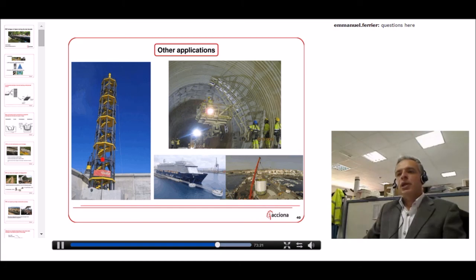The columns are made of carbon fiber pipe produced by pultrusion. The floors here are glass fiber sandwiches manufactured by Resin Infusion. Here you have these stiffening rings made by glass fiber pultruded pipes, and these slabs made by carbon fiber laminates produced by Resin Infusion. And this spiral staircase here, the steps are made by a sandwich structure made of polyurethane and glass fiber produced by RTM. It was a very interesting project.